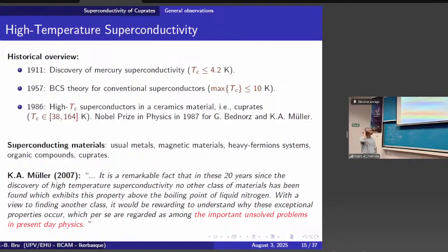The first microscopic theory, which was a breakthrough, was the BCS theory for conventional superconductors. They found mercury, but then they found there is superconductivity in aluminium, in lead, and the temperatures to get this are of the order of 1 to 10 K always. So it's very small temperatures, very difficult to reach. And the microscopic explanation was given by BCS, Bardeen-Cooper-Schrieffer theory in 1957.